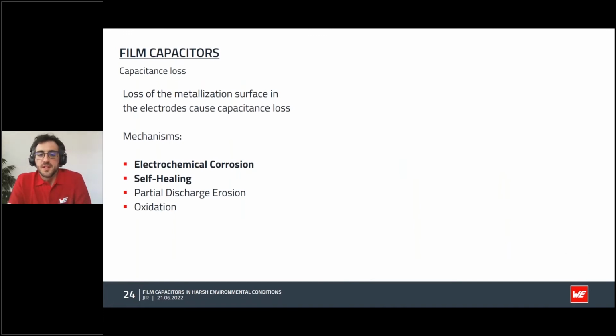What is happening inside the capacitor? There are many mechanisms that cause a reduction in the metallized surface. In the end, because the electrode surface is smaller, the capacitance drops. The electrochemical corrosion is driven by the combination of voltage and humidity. Due to imperfect sealing, water vapor will permeate and cause corrosion, which will appear in the dielectric as spots. This is the main phenomenon affecting the capacitors during the damp heat test.